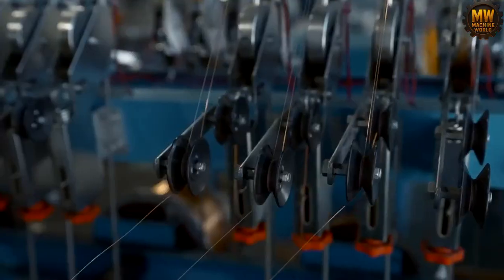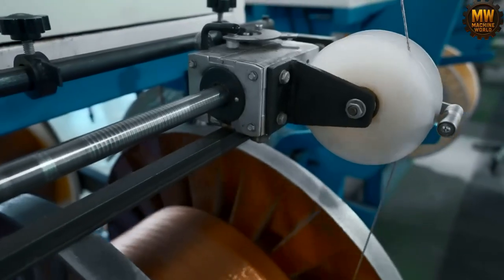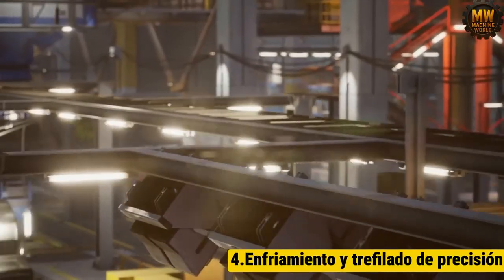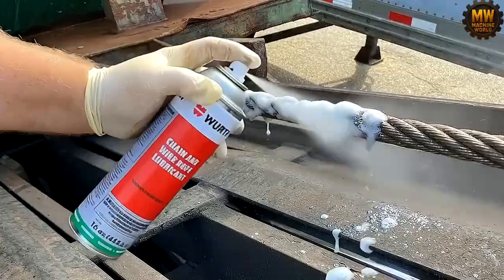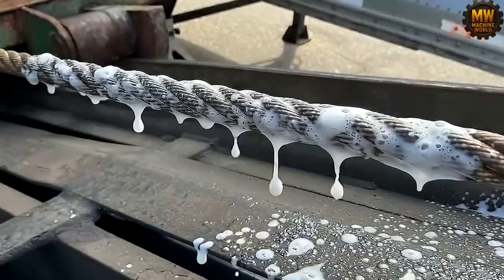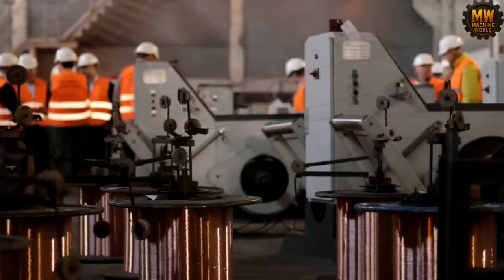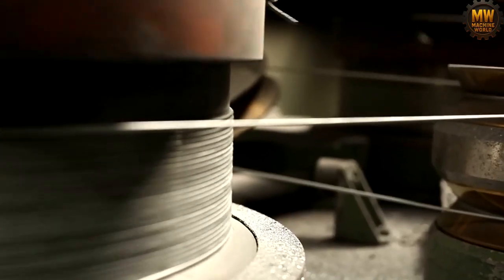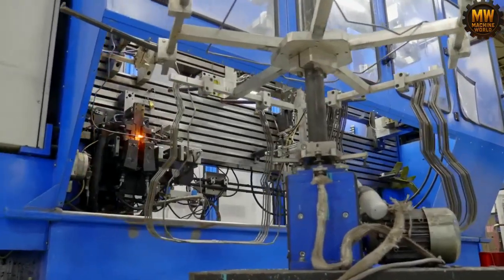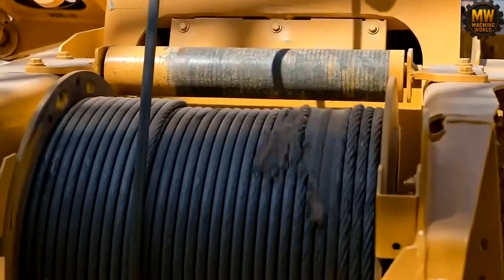The machinery deforms the metal at room temperature. This triggers a counterintuitive physical law known as strain hardening. By forcibly compressing the crystal lattice, the process causes structural dislocations inside the iron matrix to pile up and physically lock together. The narrower the wire gets, the harder it fights back. Forced thinning mathematically multiplies its tensile strength to extreme limits.